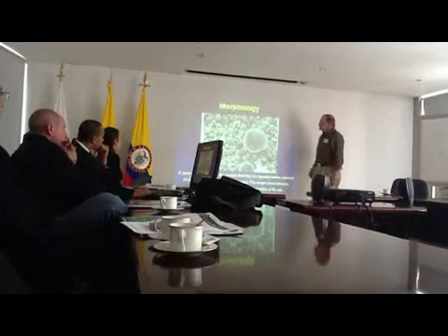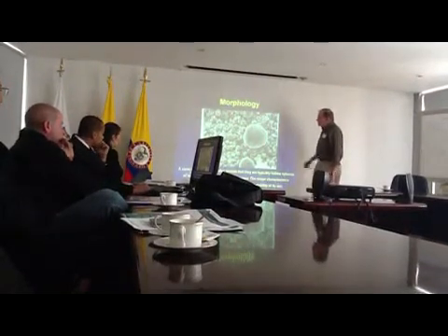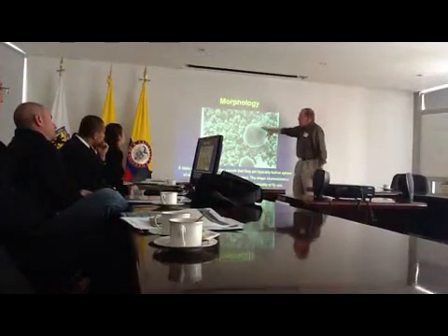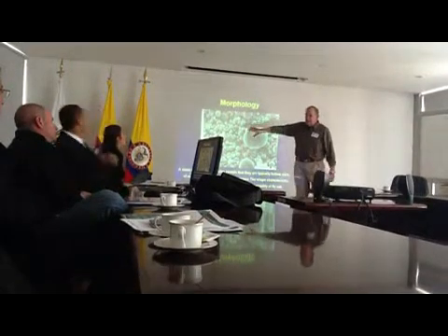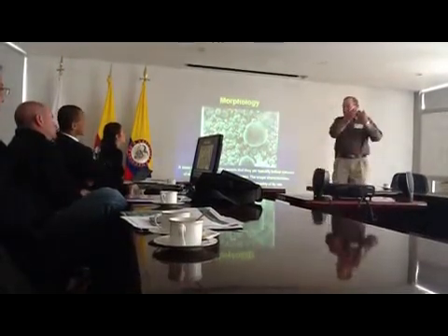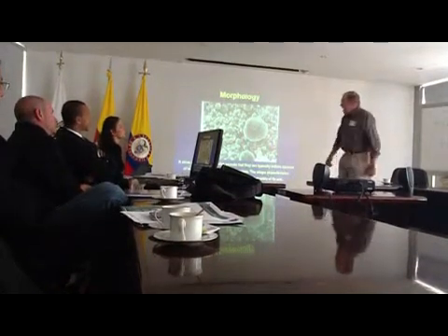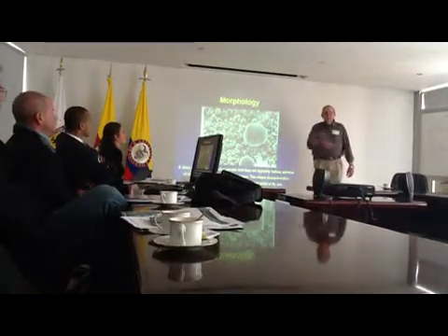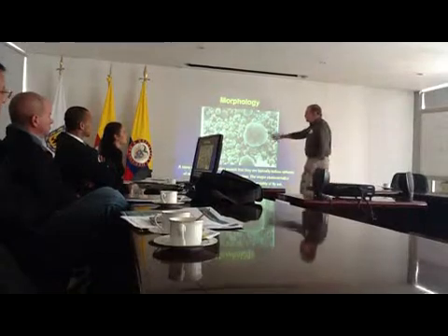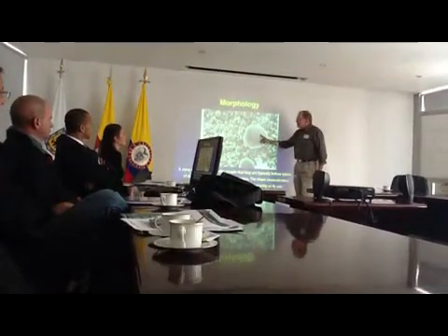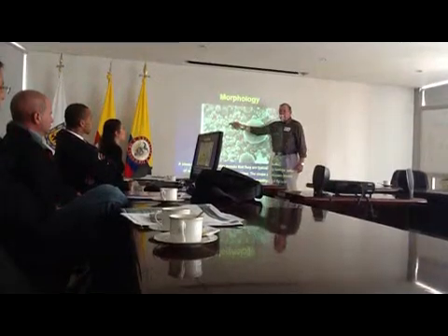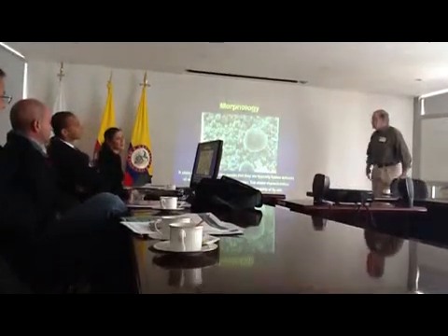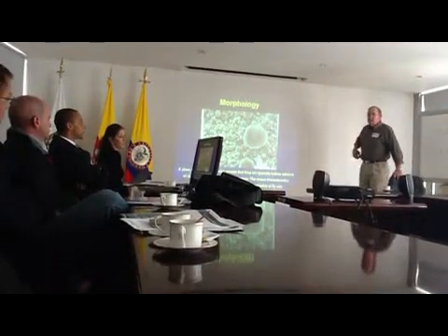Okay? The morphology of fly ash is spherical and hollow inside, but it has enough clay, which are pozzolans, and not quite enough lime to do what we need to do in stabilizing clay. So generally we mix it in combination with a certain amount of lime. And that again saves money if it's available. I'll explain a little bit. Okay?